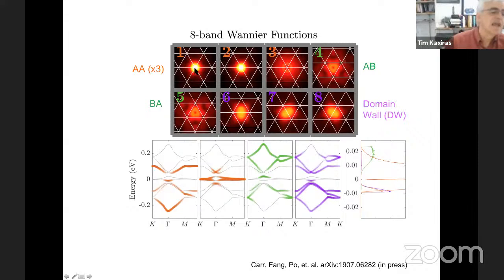So let's look at one state, for example. So this state projected on the bands has large projection on those 2 bands, and it has large projection on this part of the flat bands and large projection here. The other band here has large projection on those 2 bands and smaller projections here. The other 2 bands, 4 and 5, have large projections here and here, but also a very significant projection here. So all these 8 bands are strongly coupled, and a 2-band model just simply does not reproduce realistically the physical picture that arises from the single particle calculation.